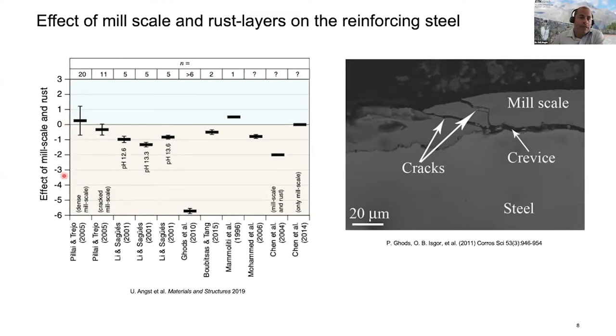And what it means here is that a negative effect means that mill scale or rust layers increase the susceptibility to corrosion. So they actually have a negative effect. A lower amount of chlorides would be tolerable if we are in this yellow area here. With the exception of 1 or 2 studies, there seems to be general agreement that the presence of mill scale and rust layers actually have a negative effect, which may be explained by a mechanism similar to crevice corrosion, which is a mechanism that Burkan Isgor and colleagues, who will also present later after me today, proposed. And this is based on the mill scale being cracked and having crack and crevice-like geometries, so that corrosion initiation in that case may be due to a similar mechanism as crevice corrosion.